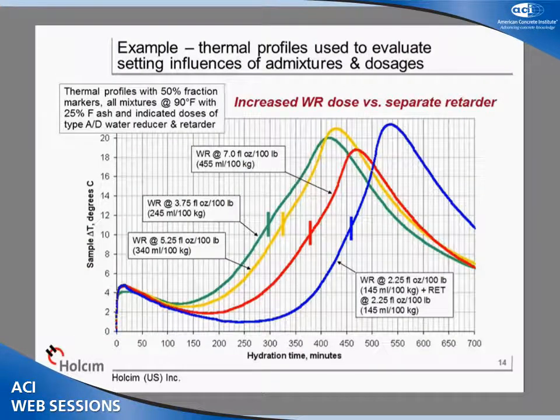Now, here's an example of how you might use this method to give yourself an appreciation of how differences in setting time are affected by different dosages of an admixture or different admixtures. And we use these references, these 50% fraction markers for each mix, to give us an indication of the amount of setting time change that would likely result by changing those proportions. Very routinely done.